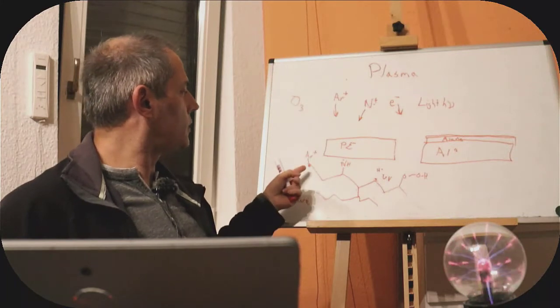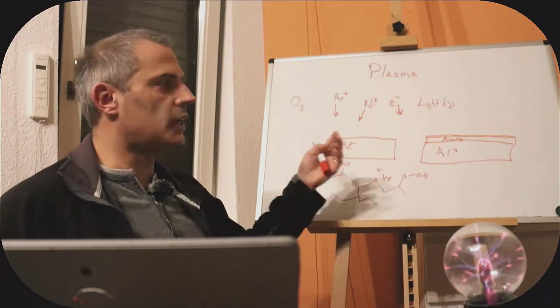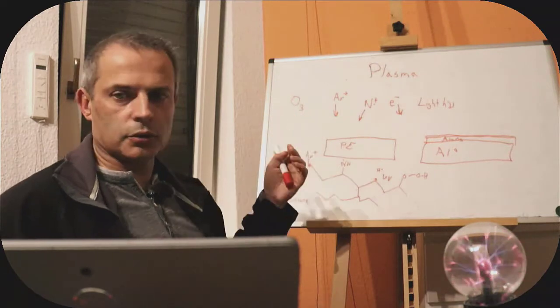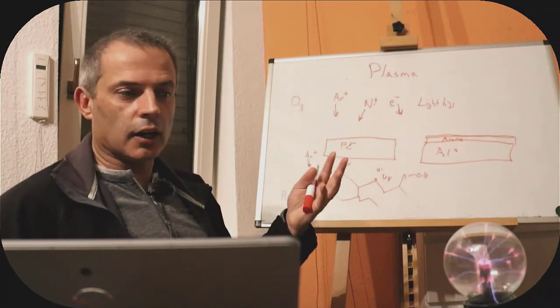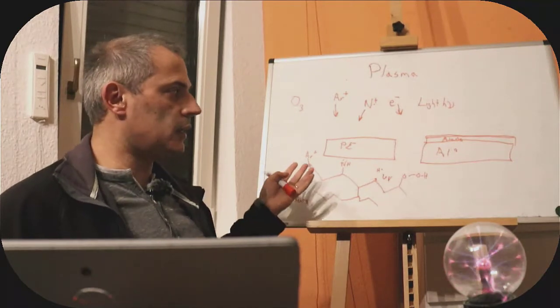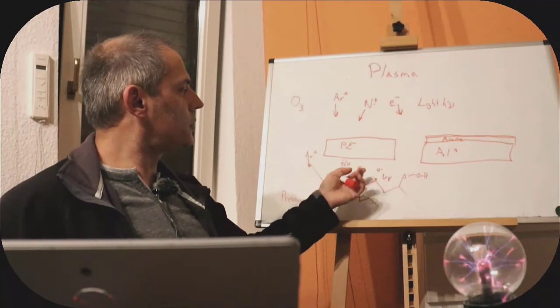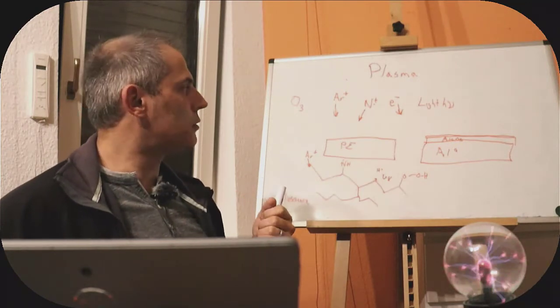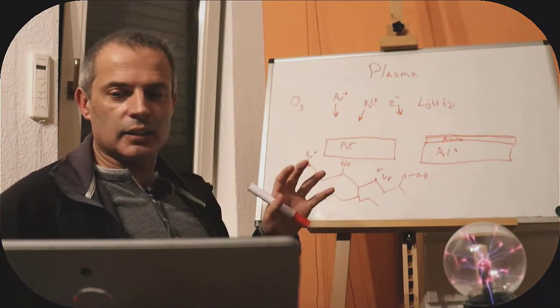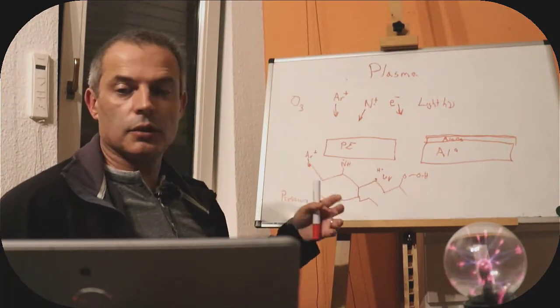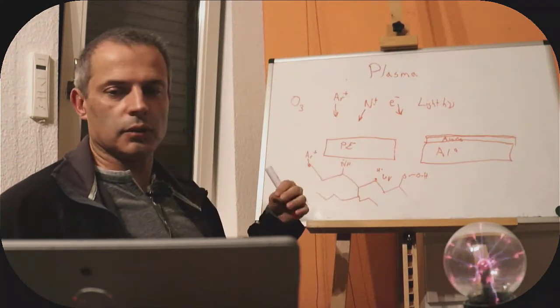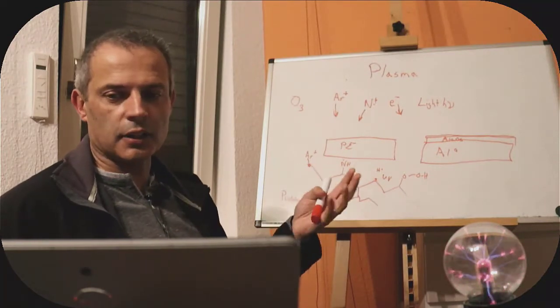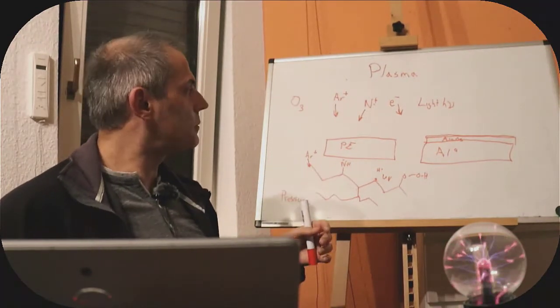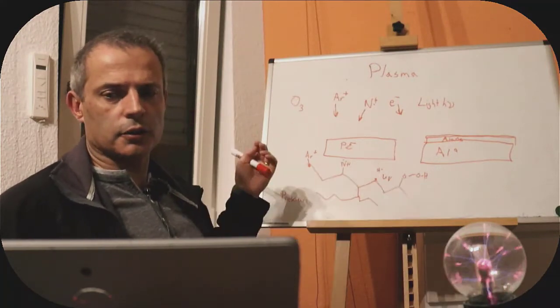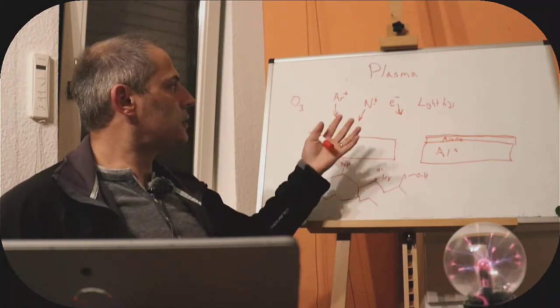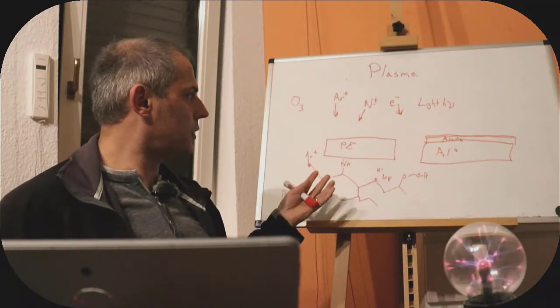If we use argon, we can just knock these off and leave radicals on the surface, and when we take it out and expose it to air, it will react with oxygen anyway. So getting hydroxide groups on the surface is usually easy. Getting amide groups on the surface or other nitrogen containing groups is possible, but a little bit fraught, because all of these reactive groups will tend to react with something as soon as we put air back in the chamber. So we may have to leave nitrogen in there for a long time to let it recover. If we want to have fluorine on the surface, we can use a fluorine containing gas. So we can use different plasmas to do different things.